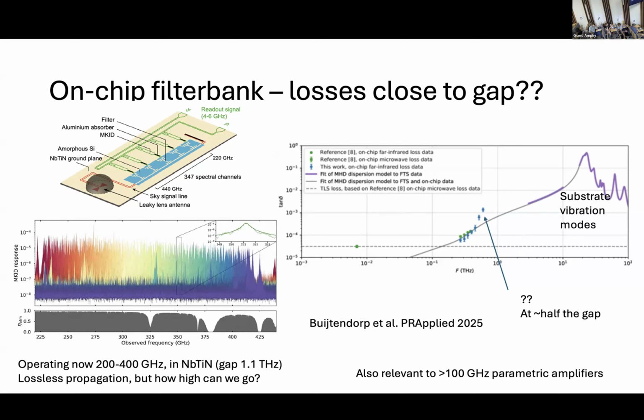And one of the devices that other people in my group are working on is where you very briefly have an antenna that is actually in niobium titanium nitride, and that's of course then lossless in principle. If you have radiation below the gap energy, then you get a traveling wave that travels onto this line, and then you detect it by having bandpass filters for the frequencies that you want to detect, and behind each bandpass filter is an MKID detector. And the MKID detector is at the moment not so relevant. It's more about what happens here on this transmission line.